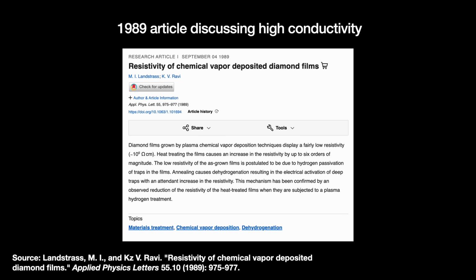But in 1989, a chance experiment with CVD diamond discovered that if we terminated the dangling carbon bonds on the diamond surface, we can produce a conductive surface 1 trillion times higher than expected. What does this terminology mean?